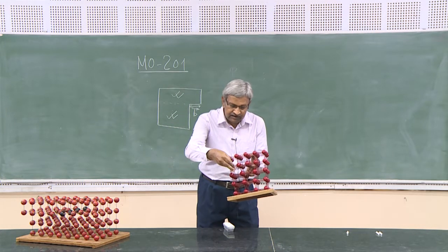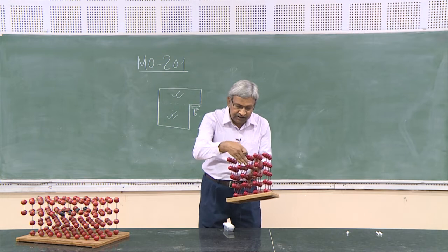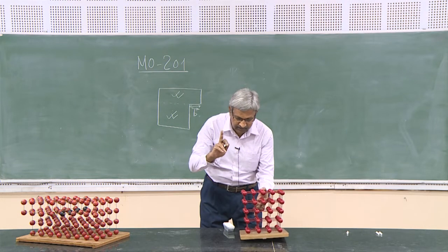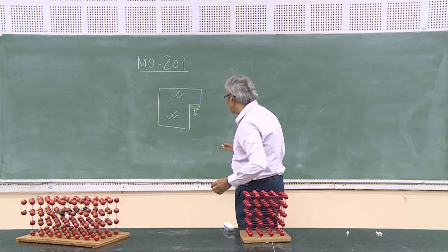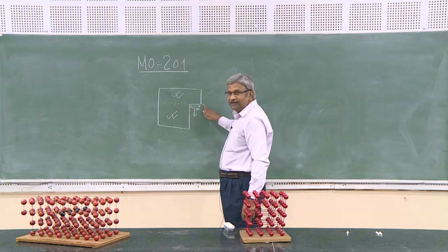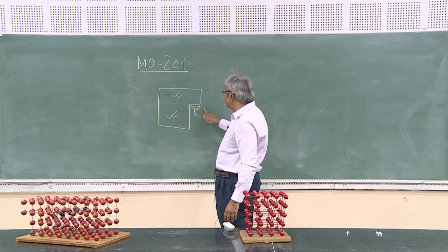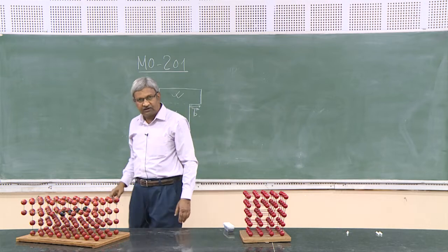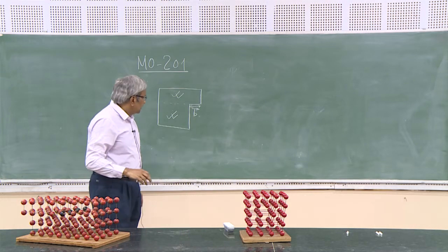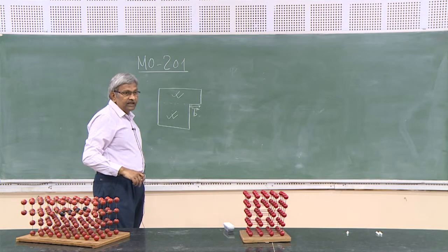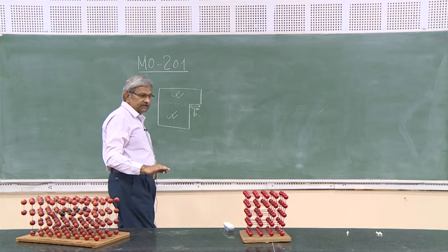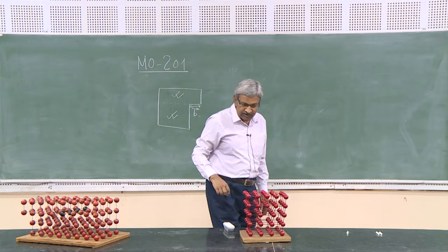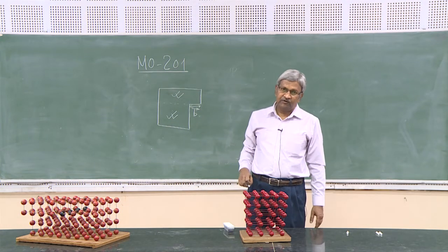As a consequence of this, it has become a perfect face, but with a permanent step getting created, and this permanent step will remain even if the force is withdrawn. Therefore, dislocation is the most important agency for permanent deformation or plastic deformation.